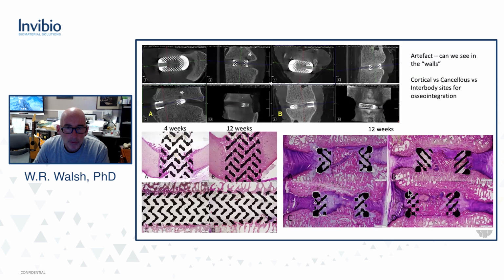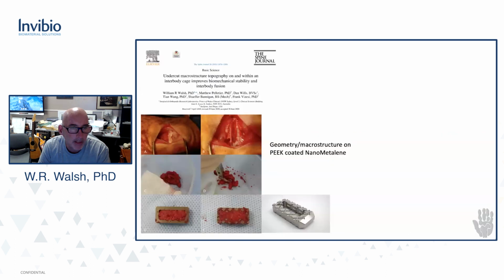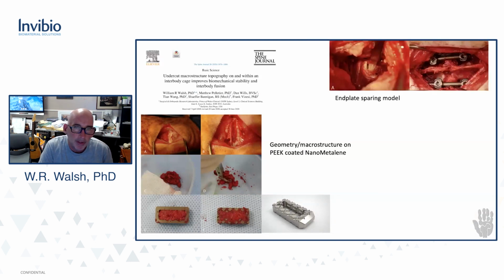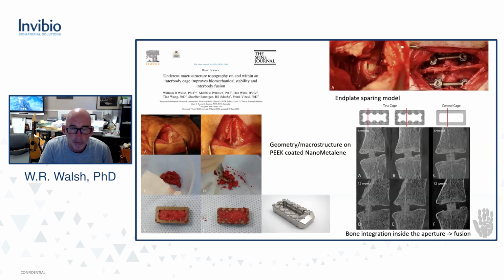And when there is bone in the walls, it's very difficult to differentiate it based on CT scan or micro CT scans. And then a final quick study. Again, this is a study that Matt and I did with our team and Frank Vaccaro and Schaefer from C-Spine. This is a macro topography implant where fixation is dictated by the geometry and macro structure. This is PEEK coated with NanoMetalene, which is a thin titanium coating. And again, end plate sparing model backed up with pedicle screws.